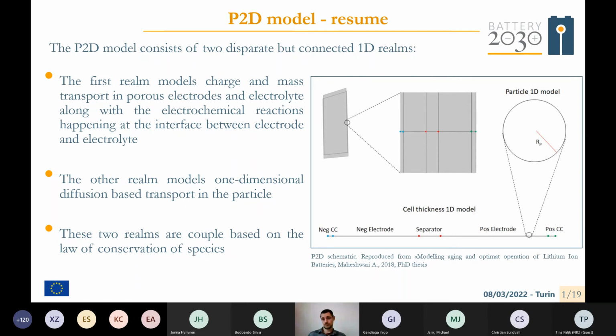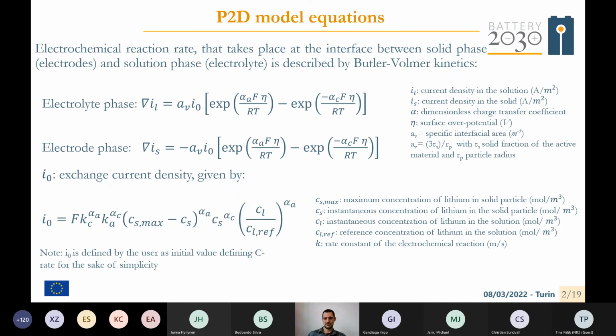This model can also extend to more dimensions, because as you can see in this picture, the dimensions taken into account here are the particle radius and the thickness of the cell. The model could also extend to more dimensions, taking into account, for example, the section of a cell, or directly the 3D dimension of the cell. For the specific application, we implemented the P2D model in a real 2D realm. Here is a reminder about the main equations used in the model. Electrochemical reaction rates that take place at the interface between solid phase and solution phase are taken into account by Butler-Volmer kinetics, both for the electrolyte phase and the electrode phase.